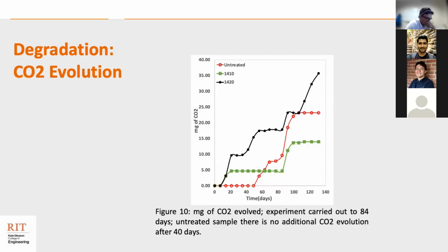The 10-second treated sample flatlines after that, which we hypothesize means that the plasma treated region of the film actually degraded away, and that is why the flatlining occurred. On the other hand, the 20-second plasma treated sample is doing pretty well and shows better signs of degradation. This, combined with the SEM images, proves the hypothesis that plasma treatment is actually accelerating the process of degradation for these films.